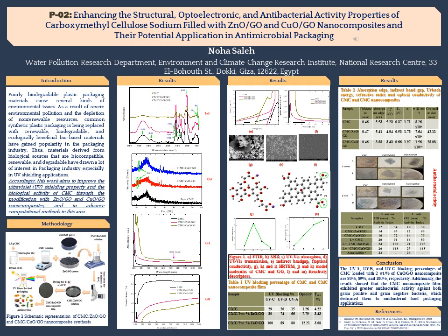The hybrid nanocomposites were characterized by Fourier transform infrared spectrophotometer, ultraviolet visible spectrophotometer, scanning electron microscopy, energy dispersive X-ray spectroscopy, and X-ray diffraction. Significant interactions between CMC and the metal oxide, graphene oxide nanocomposites were revealed by Fourier transform infrared analysis, which reflects the formation of hydrogen bonding between CMC and the nanocomposites.